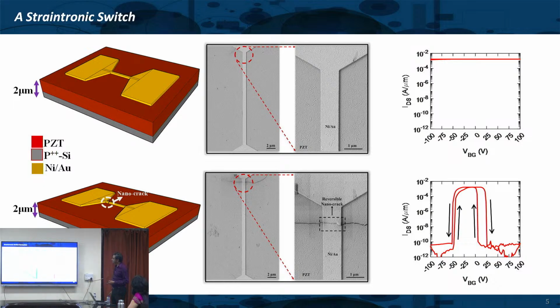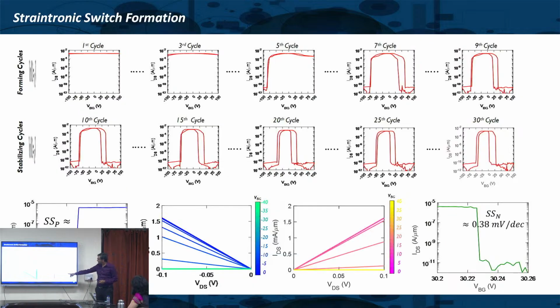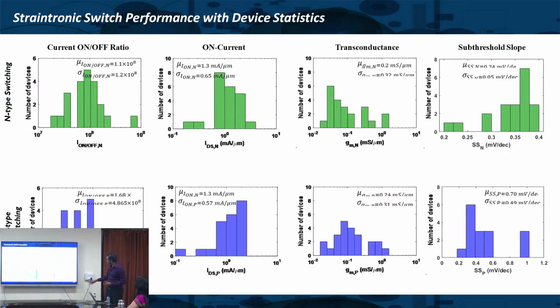Look at the numbers over here. Subthreshold slope, this is probably not the best device, 0.42, already 100 times better, correct, in these devices, but this actually requires a forming. You have to do a multiple process. We will not go into detail of that, right? And look at the on current. The on current numbers are milliamps per micrometer. You cannot achieve this even with the silicon technology, right? I mean, this is what the silicon technology can only aspire to do, right? And we get very high GM, off current is very low, right? Literally limited by the noise floor of the instrument.